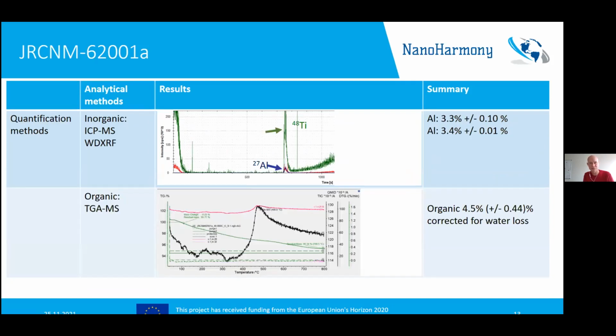And this is for quantification. We see how ICP-MS nails the aluminum and titanium from the core. And we also see how TGA-MS, by looking at the mass loss, which is the green line here, shows the organic content.